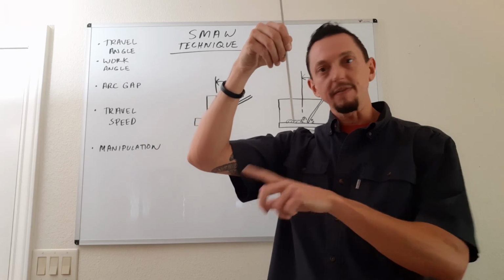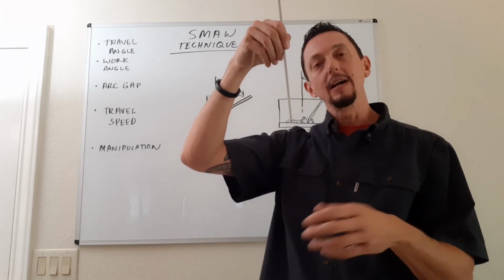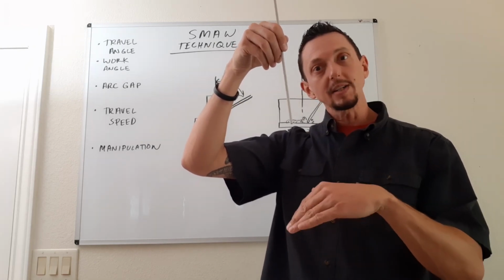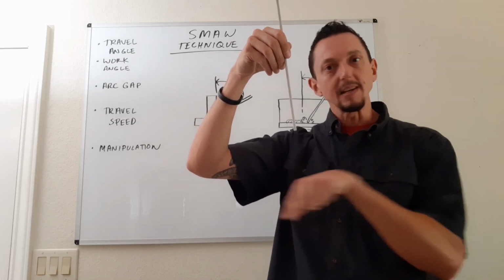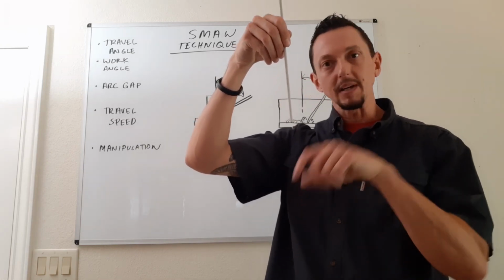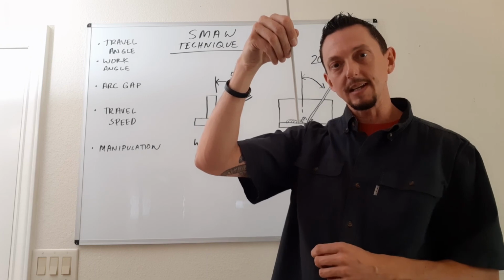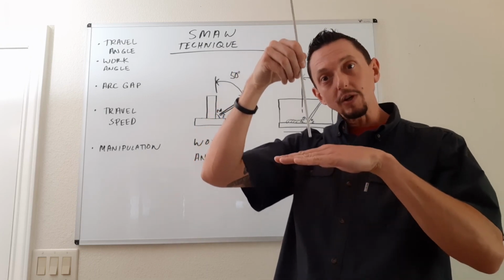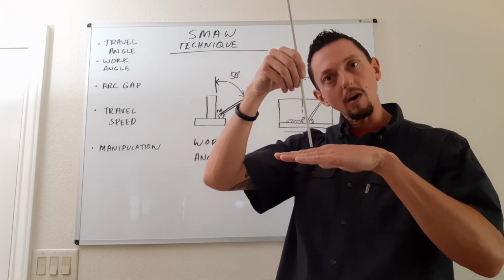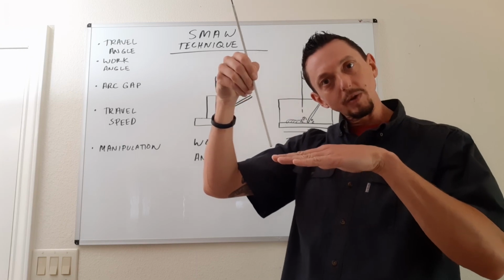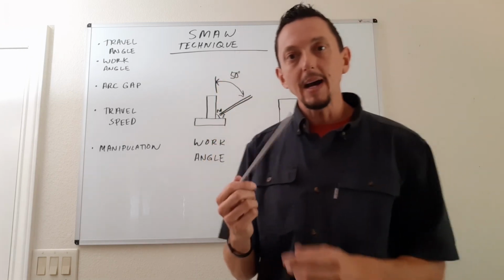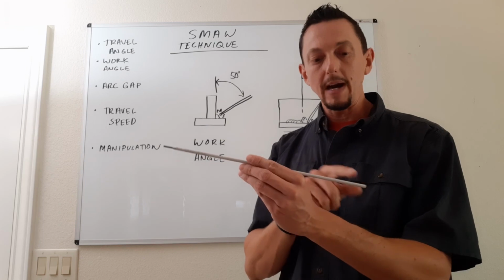The weld metal starts to fly all over the place, a spatter. It doesn't deposit where we want it to go. It creates undercut because that arc is kind of wandering around because it's trying to find the path of least resistance. So we need to make sure that we're maintaining a very short arc gap as we progress through the weld. Now, keep in mind, this is a consumable electrode, right?